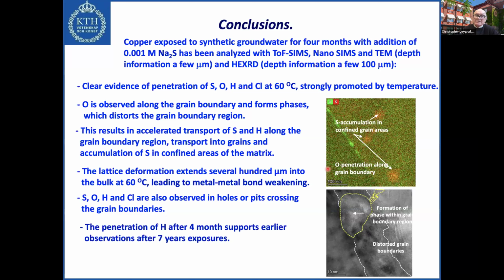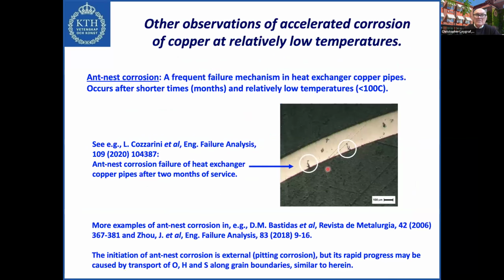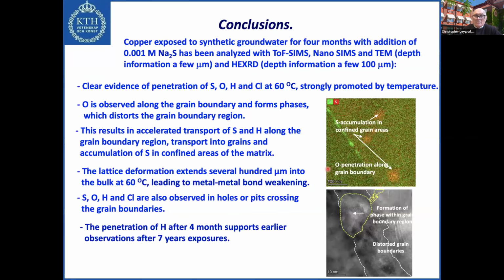And the penetration that we see of hydrogen after 4 months supports, can we say, early observations up to 7 years. Of course, the rate by which hydrogen penetrates is not any simple fixed diffusion laws. These are very complicated rate laws. Of course, when we found these results, we were to begin with quite surprised. We didn't expect that there would be penetration so high at 60 degrees.